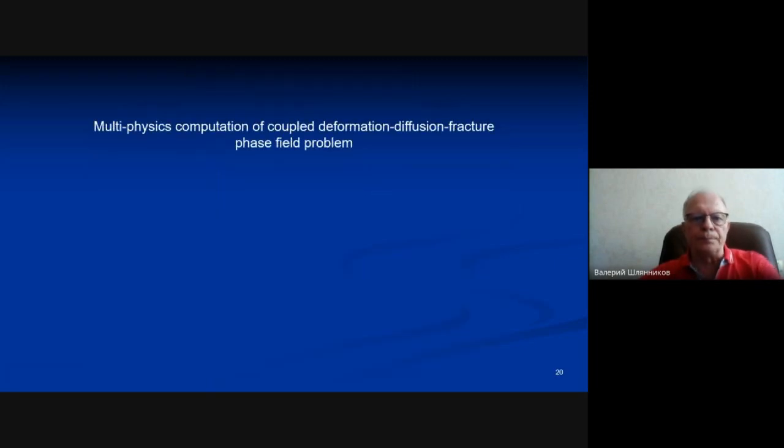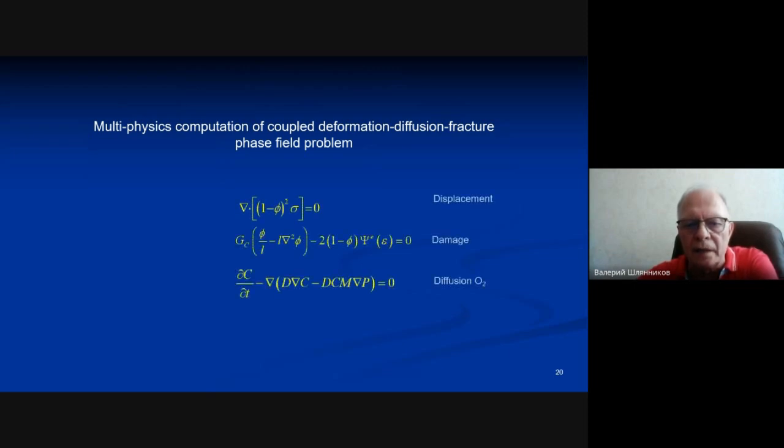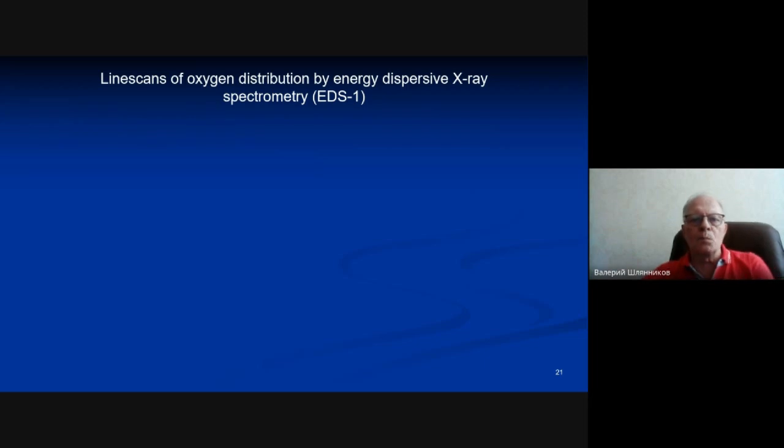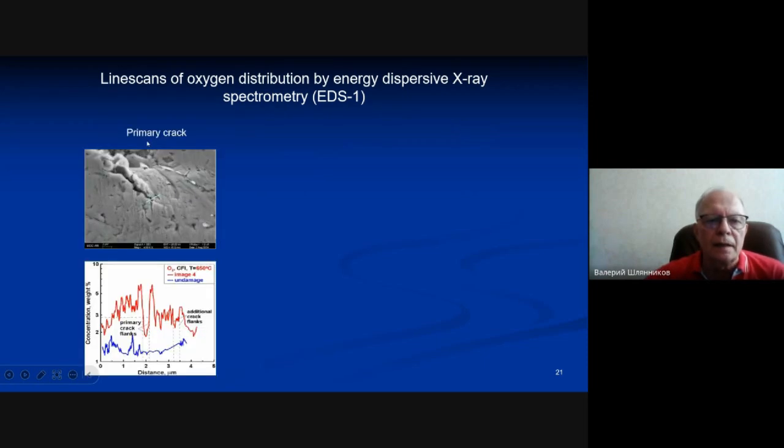And in order to perform multi-physics computation of a coupled deformation, diffusion, fracture phase field problem, it is necessary to take into account and model the diffusion process, for instance, hydrogen or oxygen diffusion into the crack tip region. To this end, we employed the energy dispersive method to analyze oxygen diffusion in the crack tip.